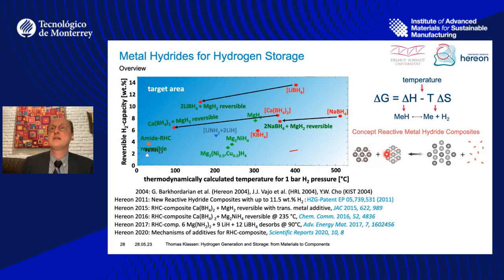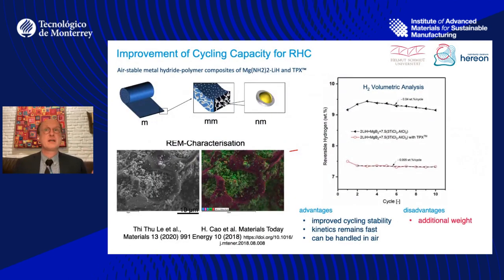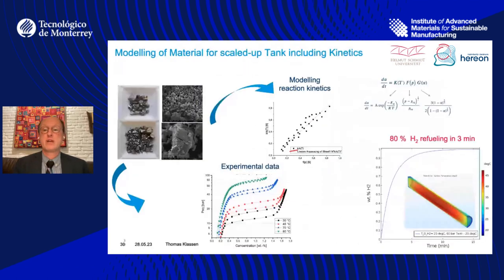We combine two metal hydrides and offer partner exchange. So the metal atoms react with each other to form an intermetallic compound, and that releases heat and helps to supply the temperature for hydrogen release. So because we now have two materials diffusing, kinetics are a little bit difficult. So what we did is we encapsulated the metal hydrides into a polymer shell that's transparent for hydrogen, and in this way kept the reactants together. So the reversibility is good, and kinetics also stay in a good range.